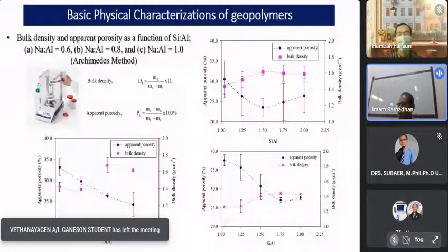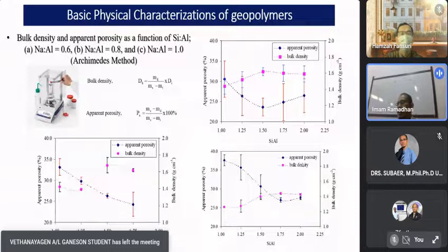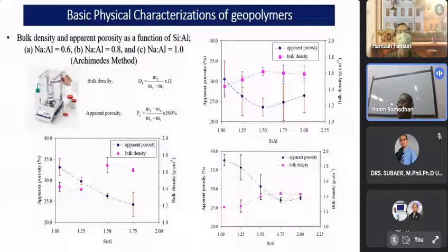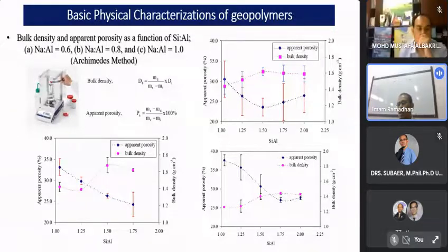Next, when you produce your geopolymer, please don't forget these two measurements immediately. So on the day that you produce your geopolymer, please remember to measure the bulk density as well as the apparent porosity of your geopolymer by using a very simple method based on the Archimedes method. You just need water, heat the water up to 100 degrees Celsius. Then you use a nice balance in order to measure the mass of the geopolymer in a dry state. When you immerse it into the boiling water, etc., then you can find your bulk density as well as apparent porosity by using very simple equations.